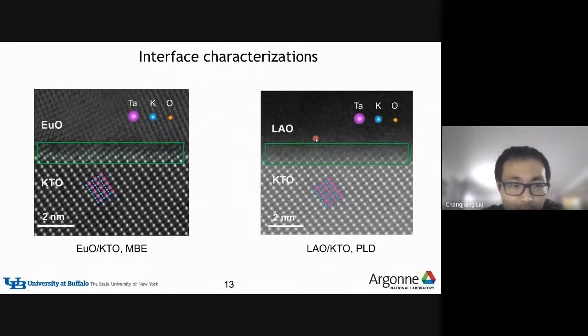scanning transmission electron microscopy. Showing on the left is the STEM image, which shows the interfacial region of EuO and the KTO. So you can see a clear interfacial region. And for LAO KTO, as I mentioned, you do not see the atoms for LAO. That is because LAO forms an amorphous phase. But still, we can distinguish an interfacial region. So in both of these cases, the top oxide materials were grown on the KTO 111 surface.